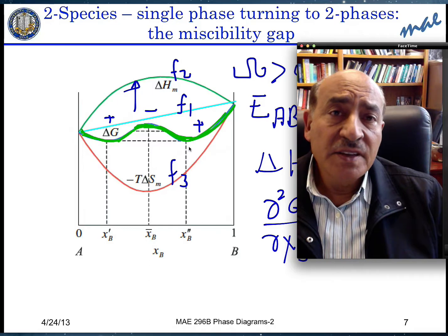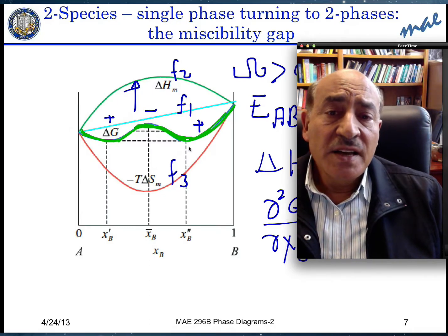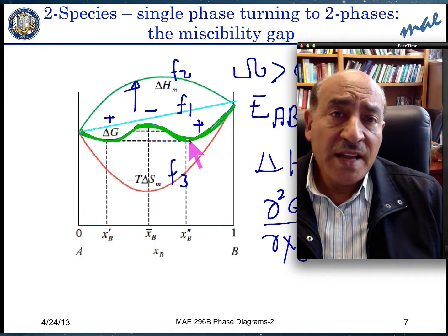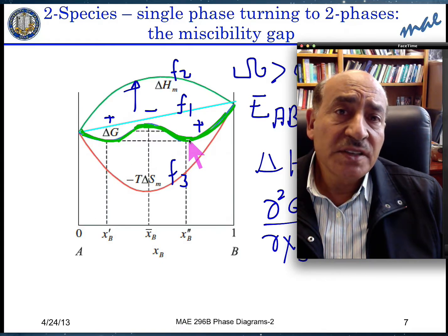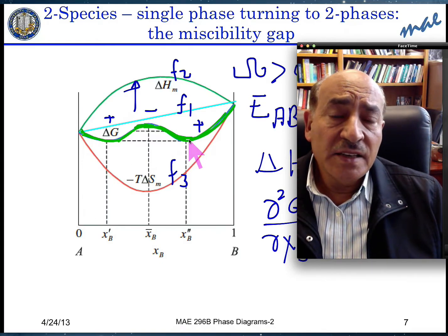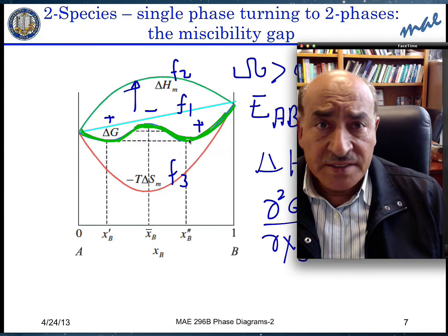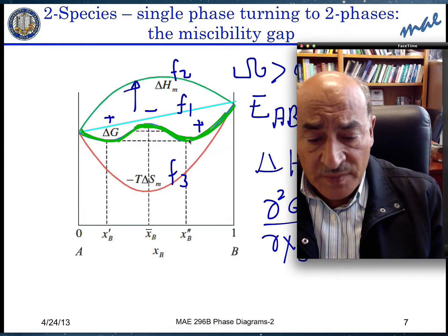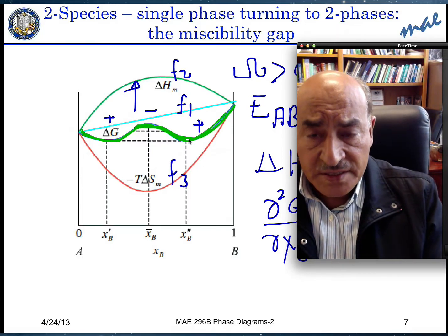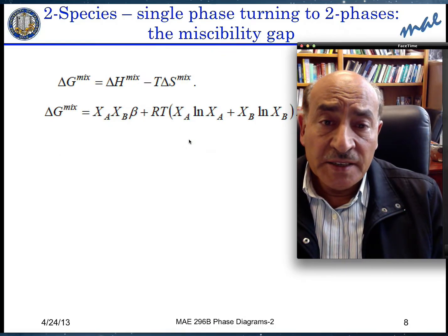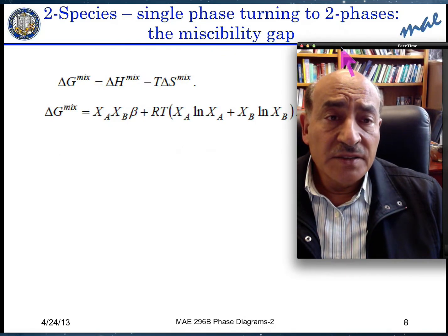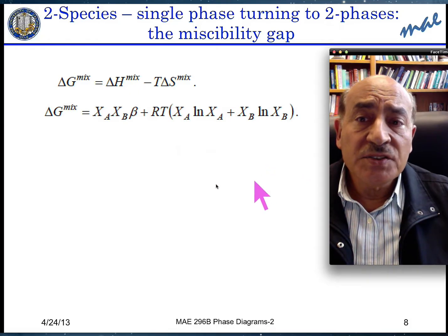So you have like kind of the striped concentrations, and between the inflection point and the minimum in the Gibbs free energy, you have a regime that has like fluctuations will grow and will separate at a smaller scale. So to show that, I'm going to now move on to the next stage and discuss it in terms of the structure of the equation.